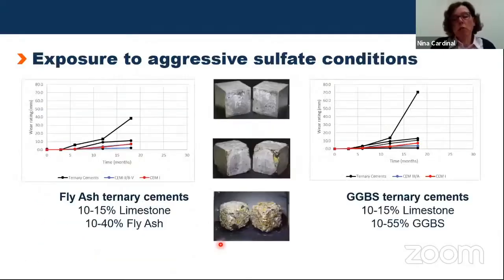On this slide, I just give you one example out of many, many tests which have been carried out of this program. So here, concrete cubes were made and exposed to aggressive sulfate conditions. You see here in the middle photographs of concrete cubes which have been exposed, virtually no wearing, some wearing, and then heavily worn cubes. On the left-hand side, you see results from the new fly ash ternary cements. On the y-axis is the wear rating, and on the x-axis is the exposure time. Up to 18 months, the concrete cubes were exposed.